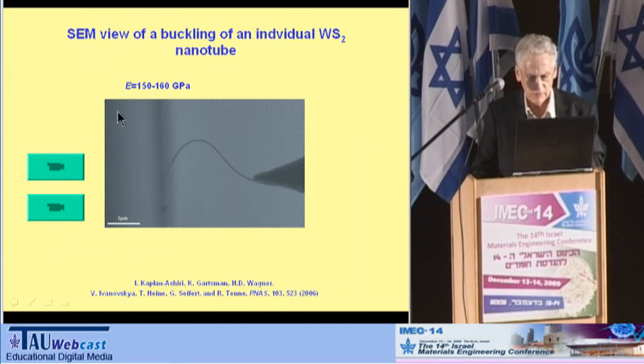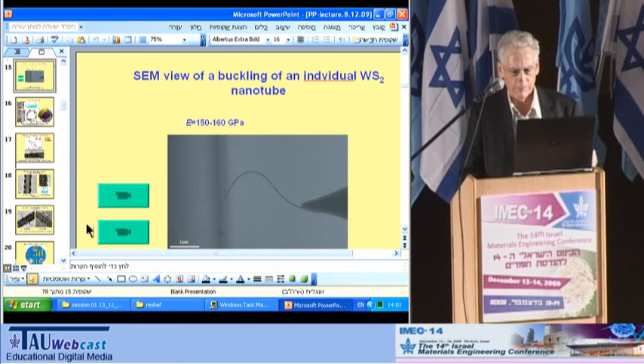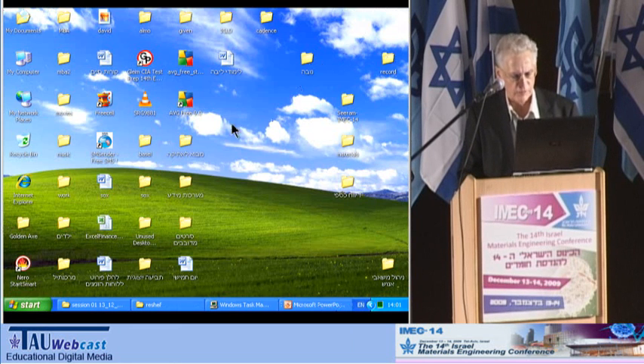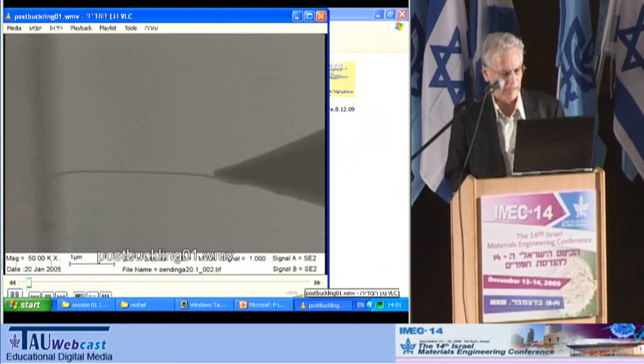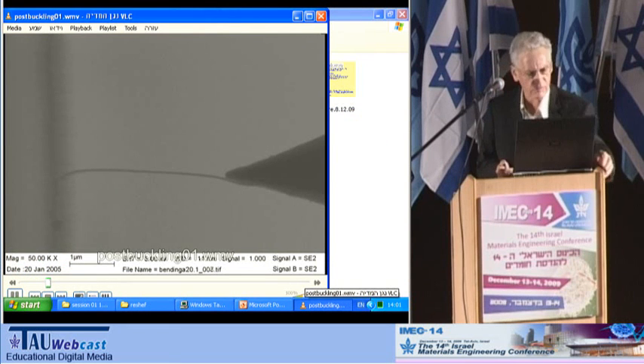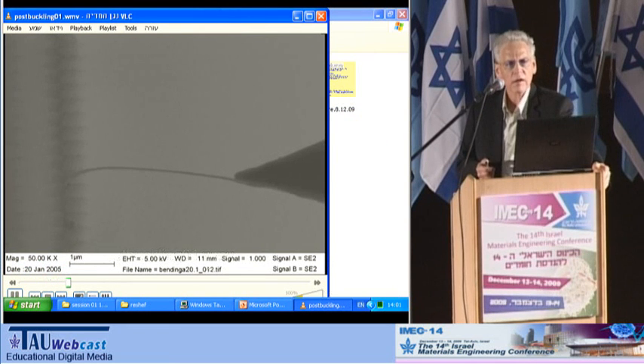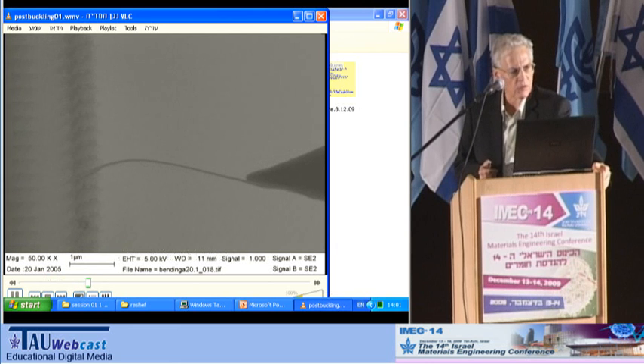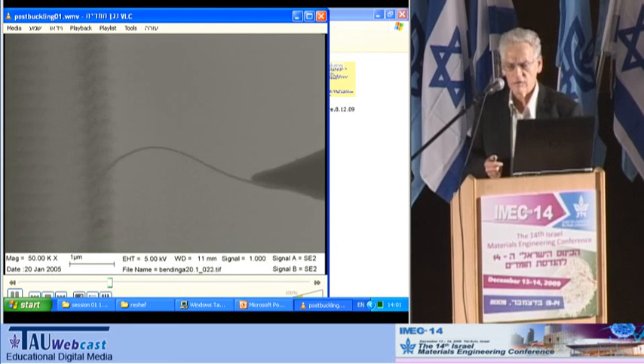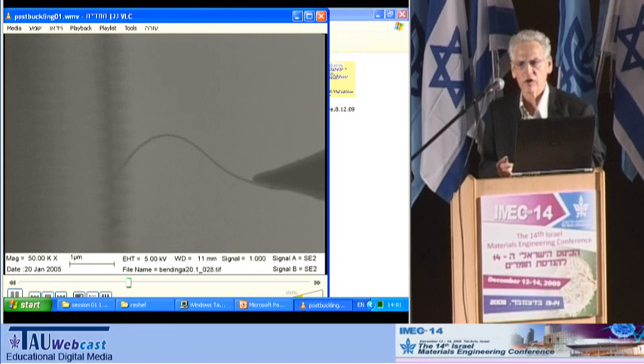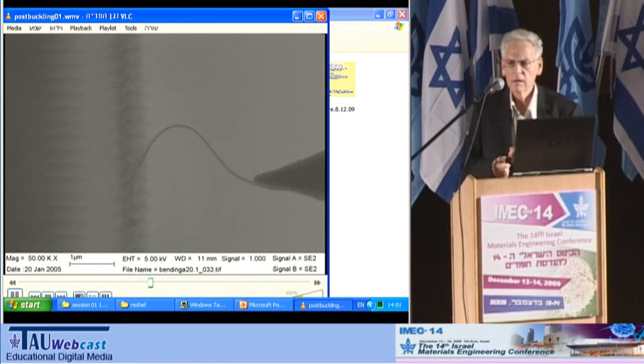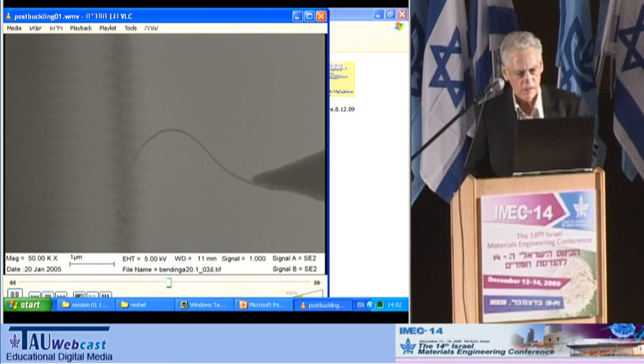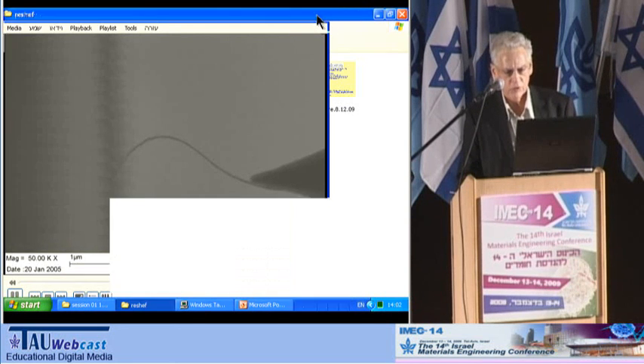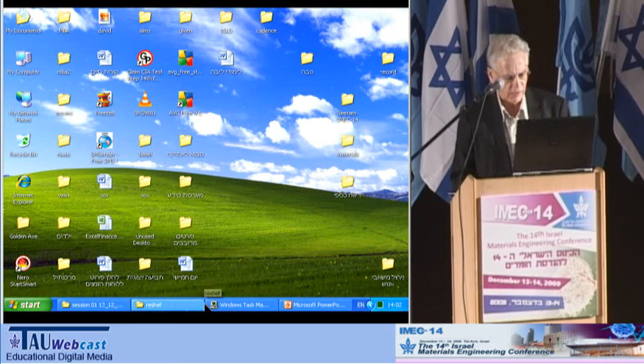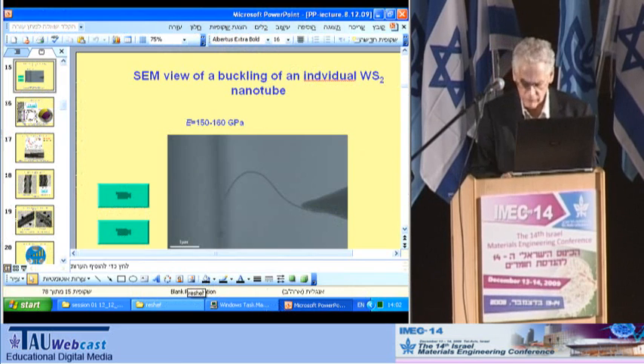So if I will be able to show you their properties, I think this is the last movie that I want to show you, the marvelous mechanical properties. That's not the best movie, but nevertheless, that's what I found. So you see that you can compress them and they will never break. The synthesis is so exquisitely controlled that basically they have no single defect, and therefore they can be bended and folded without any failure. And you can do that as many times as you wish, and statistically, you find that all the nanotubes behave more or less the same way.